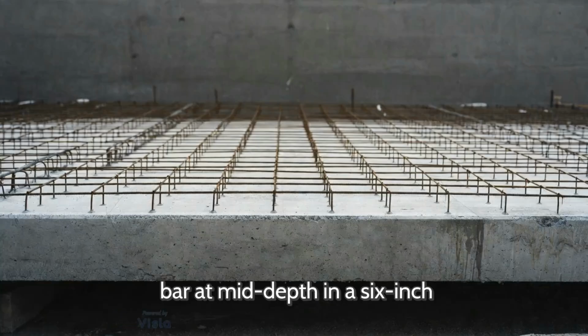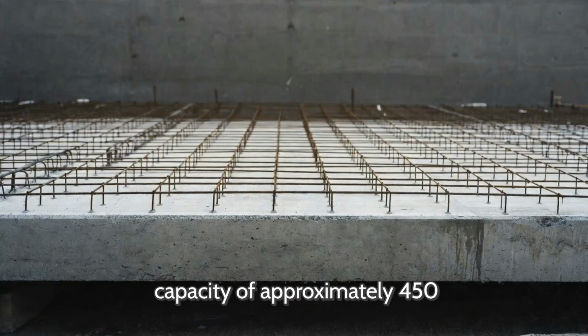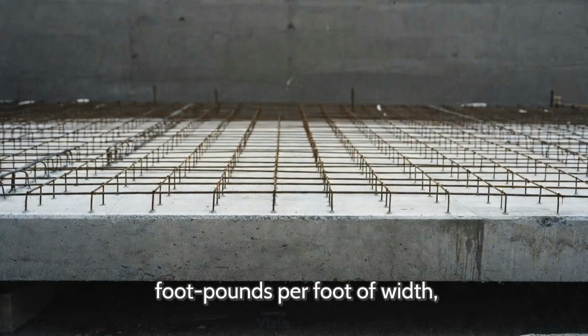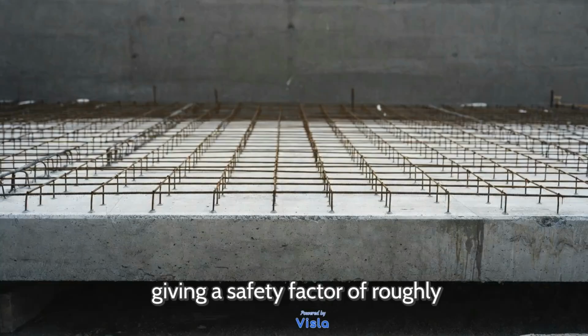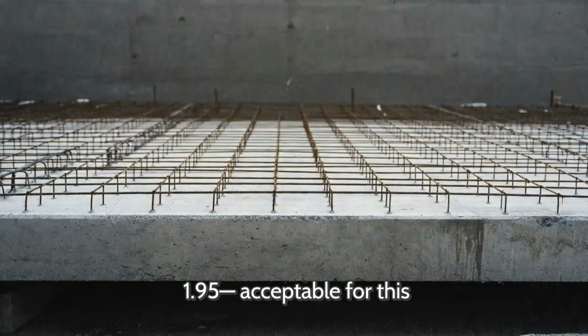The number 4 bar at mid-depth in a 6-inch slab provides a design moment capacity of approximately 450 foot-pounds per foot of width, giving a safety factor of roughly 1.95, acceptable for this application.